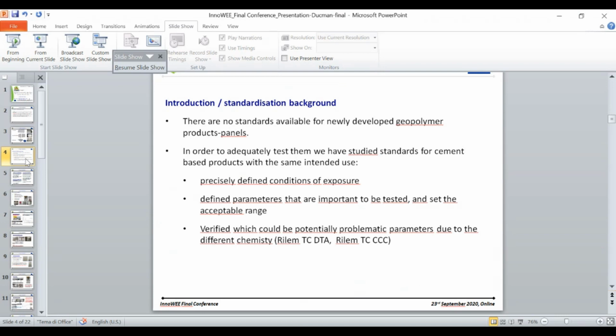In order to adequately test them, we have studied standards for cement-based products with the same intended use. And we have decided what we need to test and to which conditions of exposure the products will be exposed, like, for example, freezing. Then we have checked which parameters are important for this intended use, like, for example, mechanical properties, water absorption. And finally, we have also checked state-of-the-art literature and knowledge regarding potentially problematic parameters, because this product differs in chemistry from cement-like products. It's a geopolymer product, as was explained before, so the chemistry is not the same as for the cement-based.